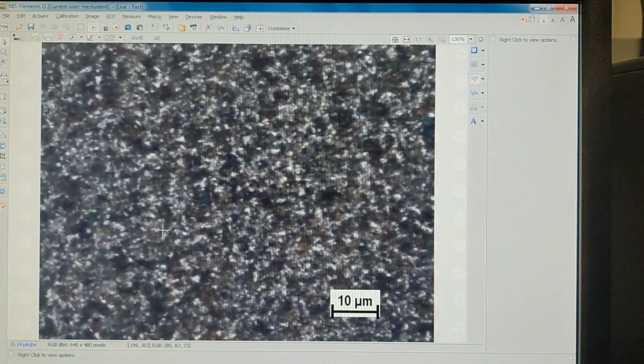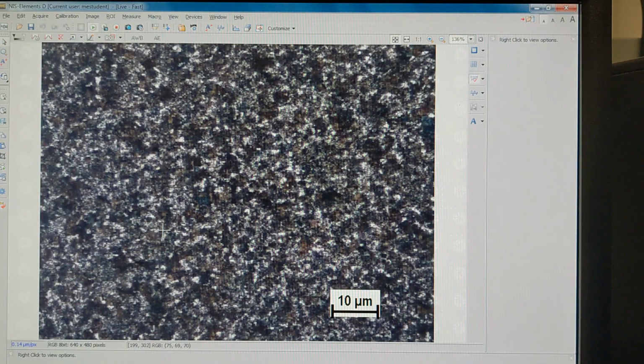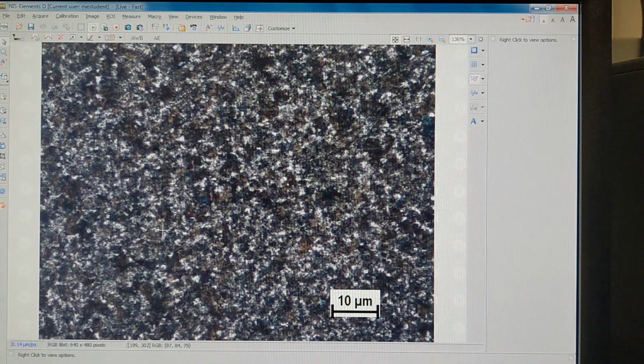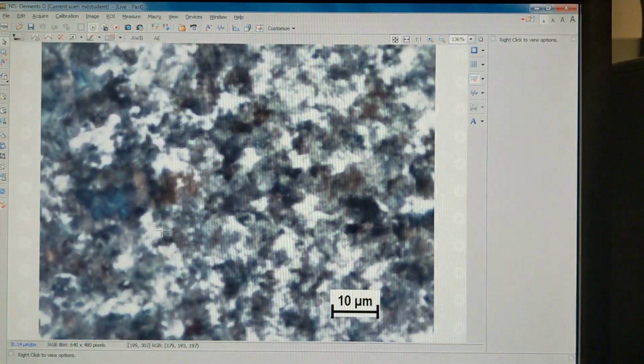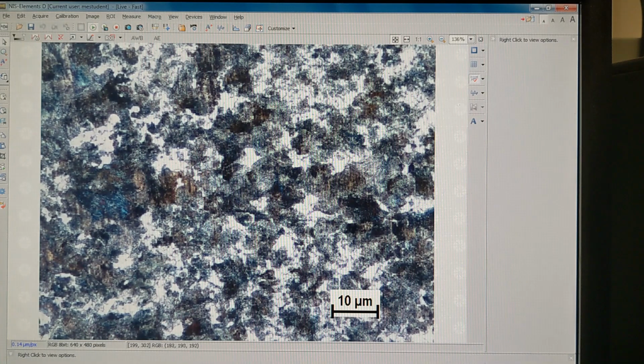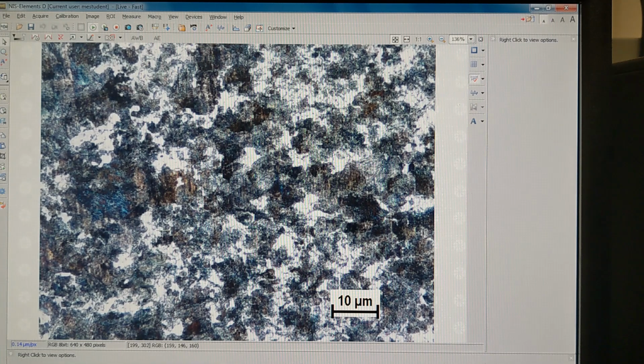Okay, and now let's look at our final sample, which is 1045 CD. 1045 CD, you might remember, has the highest carbon content, and that becomes pretty quickly obvious because this is quite a bit darker, quite a lot less light ferrite regions compared to our 1018 samples. But if we zoom in, just 20 times, let's go to 50.